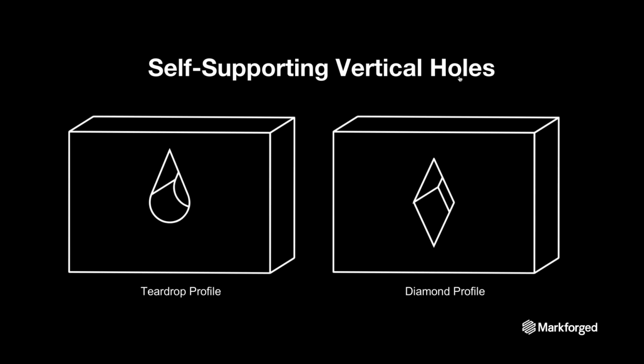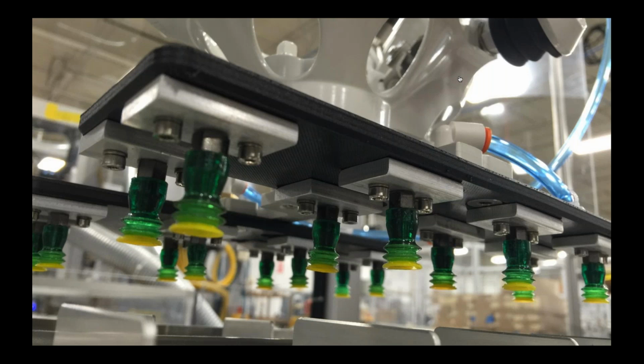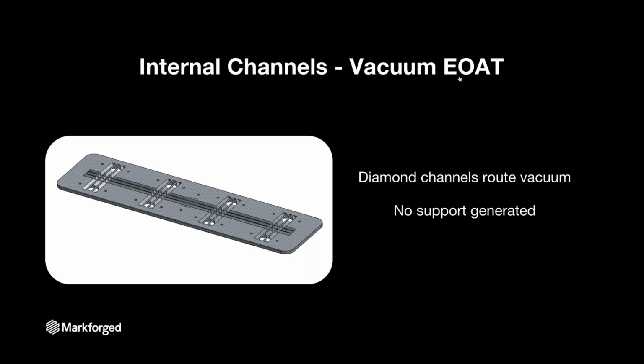So how do you get away from these support materials, especially if you're printing horizontal holes? It's creating a teardrop profile or a diamond-shaped hole. For example, this part that our customer used was actually drawing a vacuum, and that black part is what we printed. It's drawing a vacuum throughout the entire part through these diamond-shaped channels that we were able to design in and print with no support needed.